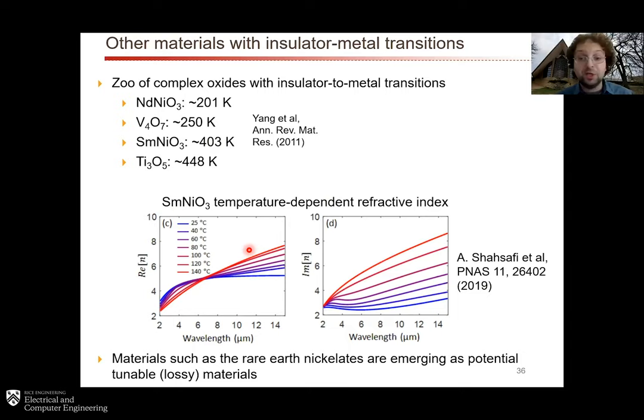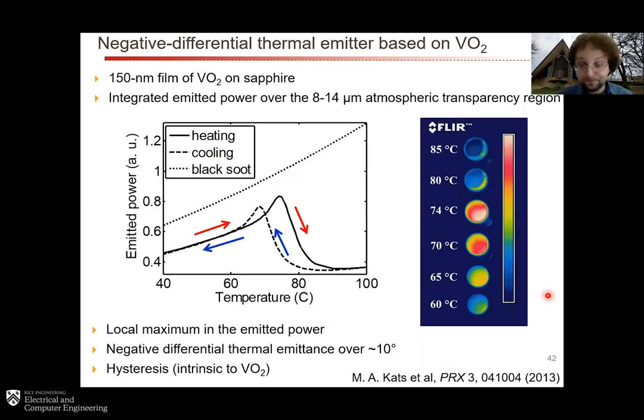And it's much more gradual than VO2, at least in our experiments, but still the change in optical properties is rather large as a function of temperature, and you can use it for thermal emission engineering, although it's probably worse for other types of optical engineering because it does not have a lossless state, unlike vanadium dioxide, which has a reasonably low loss state in the mid-infrared. So this data set, if you're interested in it, was published at the end of last year in this paper in PNAS. So you can do some really fun stuff with some of these complex oxides.